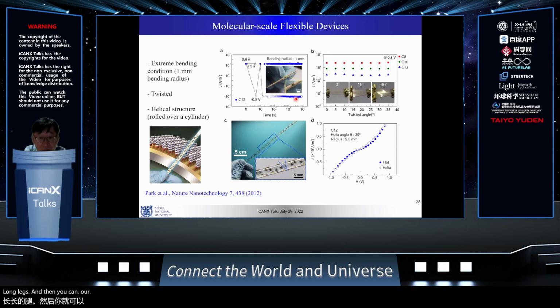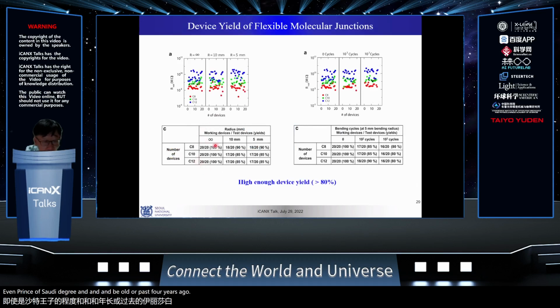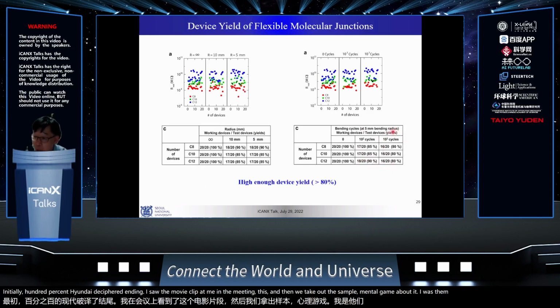And then you can line it up on a toothpick, which has a 1 millimeter radius, and we can even twist up to 30 degrees; this is all possible. The yield when you measure a flat configuration is 100%. If you bend a little more, some devices died, but still more than 85%. If you bend even more, the yield is still 85%. When we didn't do any bending cycling, initially 100%. I showed the movie clip where we repeat this 100 bending cycles, then take out the sample and measure again: about 85%, and after 1,000 bends we still have 80%.